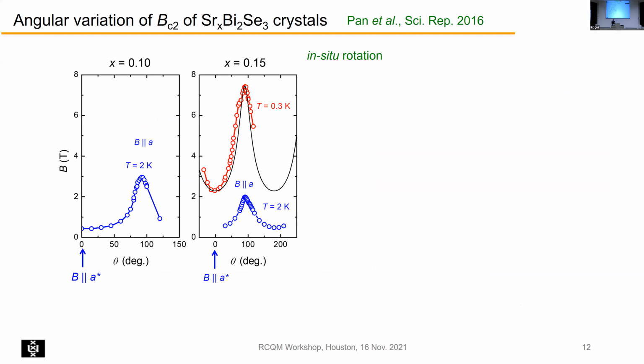Okay, so then we can directly plot the upper critical field. This is also from in situ rotation. This is for x = 0.10, and it looks like this. This is also in the helium-3 system. So we actually reproduce what I mentioned on one of the earlier slides. But here you see the whole angular dependence. The same for crystals, and twofold. So why do we have this twofold anisotropy in the basal plane? That's the important question.